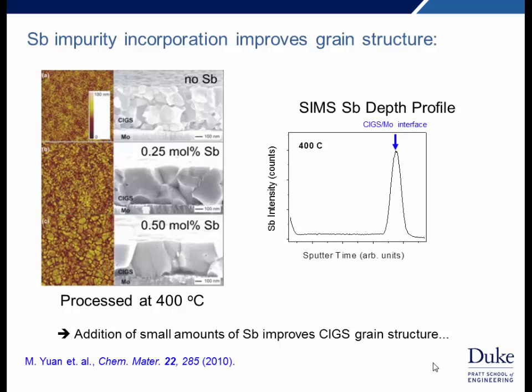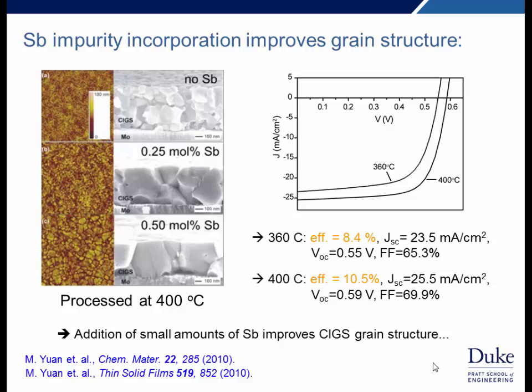And if we look at the compositional depth profile of antimony in the film using SIMS, we find that after the anneal, all of the antimony is collected at the back contact, at the moly-CIGS interface. And so the antimony introduced into this film is not actually incorporating into the CIGS, but is catalyzing the grain growth as it migrates to the back contact. And using this approach, we've been able to deposit devices with efficiency over 10%, even when processing at temperatures below 400 degrees C.